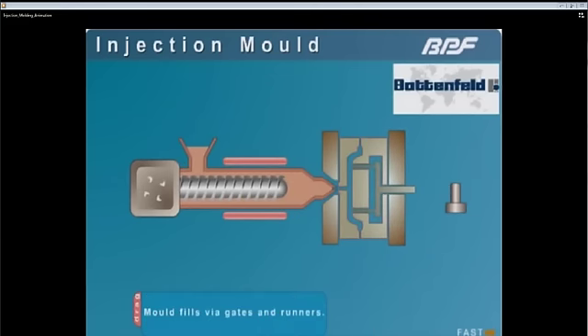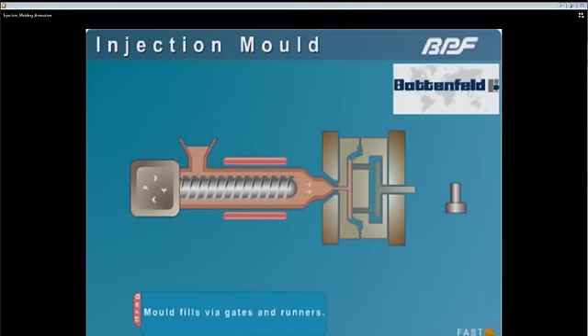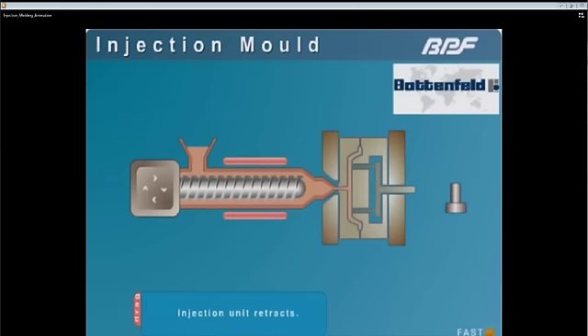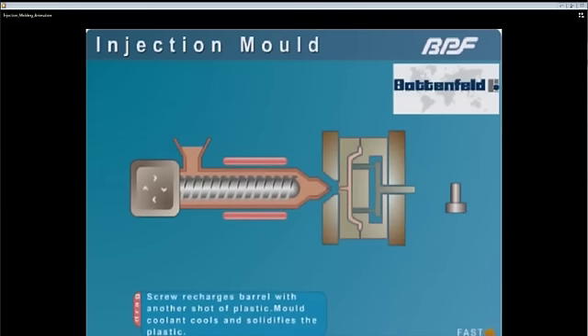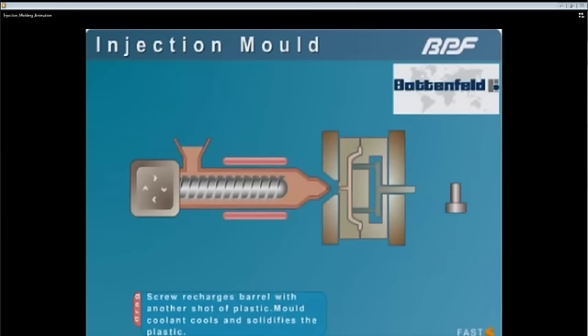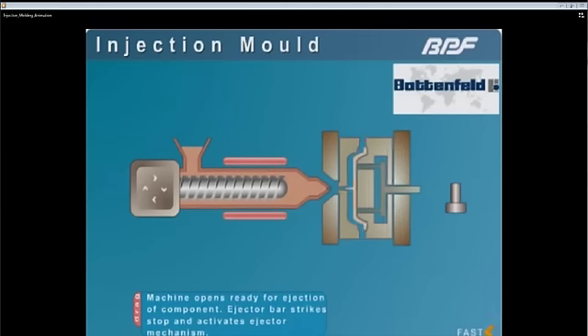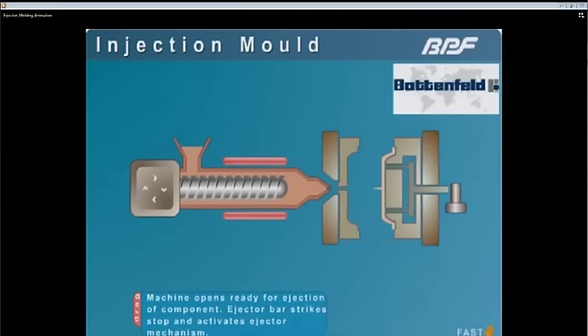The injection unit moves up to the mold, the plastic gets injected. Now we go into what we call the holding phase or the packing phase. That's where we hold pressure on the entire system until the gates freeze off, the part cools down, the screw retracts, the mold opens, and the part comes out.